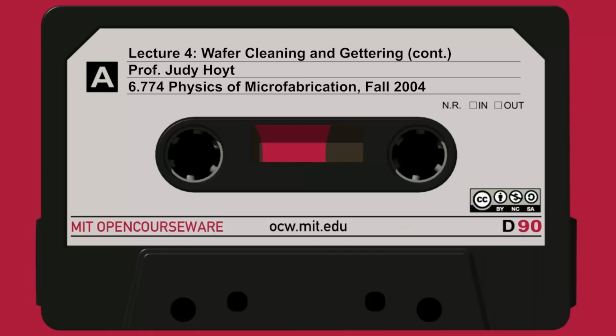So on page 20 or slide 23, I just want to summarize gettering. It's still fairly qualitative, I think you can tell. These gettering methods really haven't been changed much in the last 10 to 15 years. There is a better understanding of how it works, but we really still need better models. In the future, intrinsic gettering, this process of creating the denuded zone, either by epi or whatever, is going to dominate because the thermal budgets for IC processing will decrease, and trying to diffuse those atoms all the way to the back of the wafer, especially titanium and moly, which have lower diffusion coefficients, is not very practical. So having the gettering site close is better.